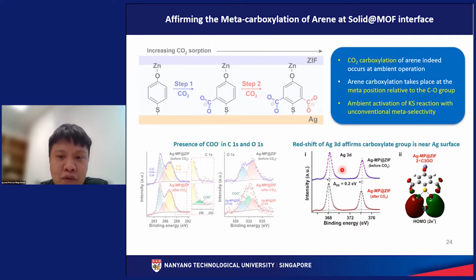To do this, we characterize our system using the Ag 3d, silver 3d XPS characterization. So upon CO2 flow, we can clearly see a red shift of the silver 3d peak towards a smaller binding energy. So to understand this phenomenon, we simulate the HOMO and the LUMO. HOMO refers to highest occupied molecular orbital, right? So we investigate the HOMO structure of our system, and from this we can see